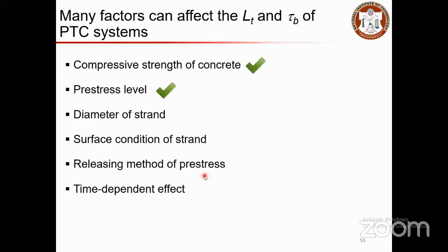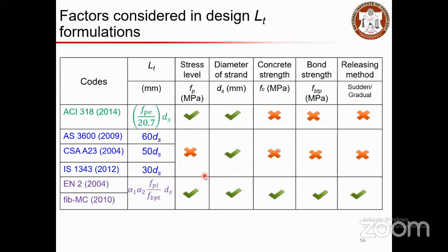But when you consider the code recommendations, not all the factors are considered, especially in the Australian, Canadian, and Indian codes. They talk about the transmission length with respect to only the diameter of the strand. So if you change the concrete strength, or any one of these factors, you will end up having the same transmission length, but the real scenario is not the same. So using these equations is not appropriate, whereas the Euro code and FIB code give you the scenario of all the factors being considered which would influence the transmission length.